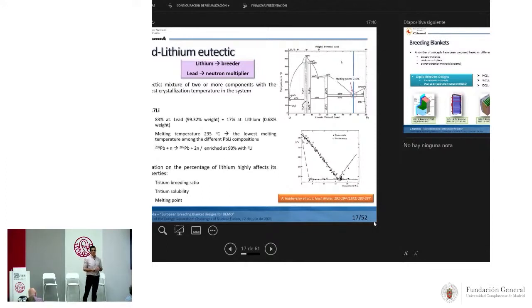The melting temperature is 235 degrees, and this is easier to manage with the piping and so on of the system, and also to maintain between the limits of operation of the structural material, which in this case is Eurofer. And also the lead, because it's a good neutron multiplier. It has a good cross-section for neutron multiplication. And what is important here is that small variations of the percentage of lithium affect important numbers in the blanket, such as the tritium breeding ratio.